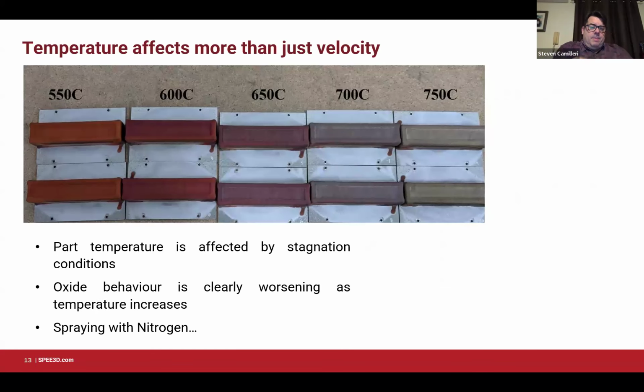All right, this is a separate observation to pressure. In this case, we've operated at our standard pressure again, 30 bar. And what we've done is we've changed our system temperature only, and we've made copper blocks at each of those temperatures. Importantly, you'll see the color of the copper changing quite dramatically. There are actually publications out there that look at estimating the oxide thickness on copper depending on its color. That is a thing. And indeed, what we're seeing is an increase in the oxide layer coating the part as a result of the part getting hotter as it was being printed.